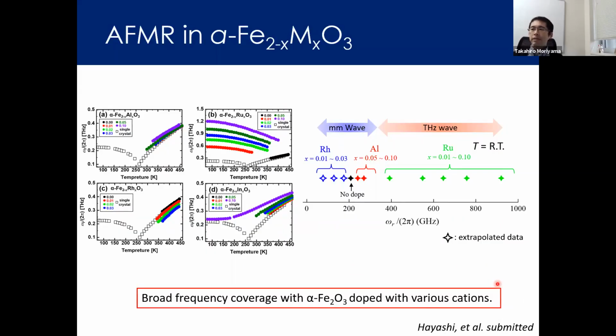So very recently, we also investigated doping effects on alpha hematite, in which one can excite the antiferromagnetic resonance as well. This material is actually not a full antiferromagnetic material, but it is a weak ferromagnetic material. It has some small spontaneous magnetization due to the DMI effect. But we can also access the antiferromagnetic dynamics in this material. Also, this material has a very strong temperature dependence of the resonance frequency, as you can see here. It changes quite a lot in this temperature range. This is basically associated with the so-called Morin transition, in which the spin orientation changes by the strong temperature dependence of magnetic anisotropy energy.